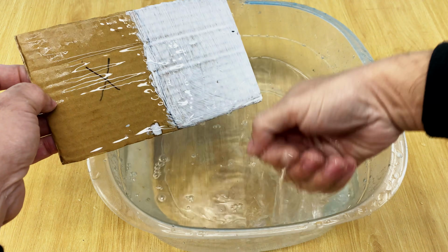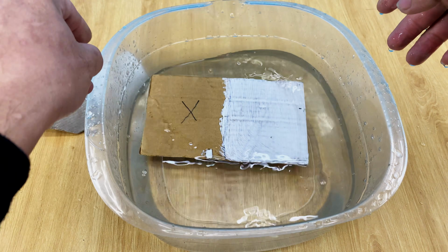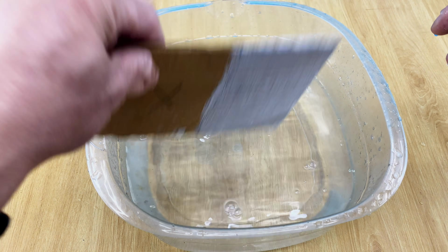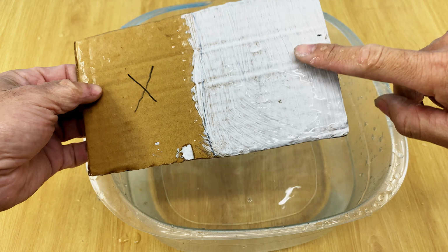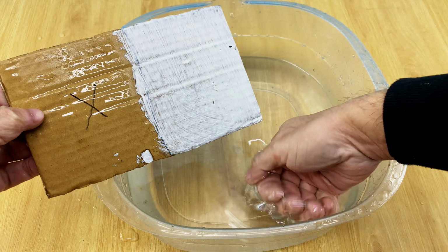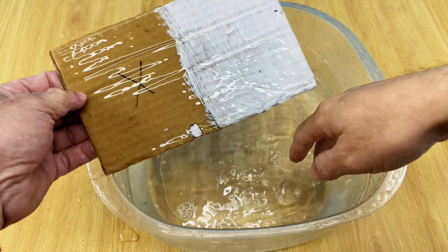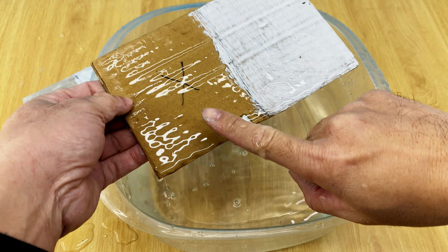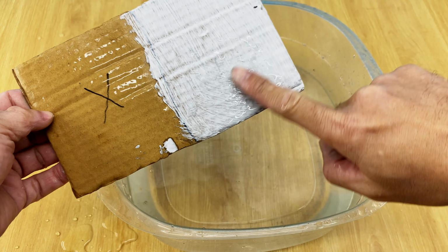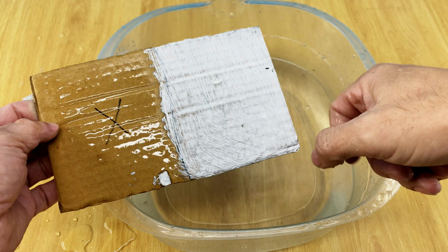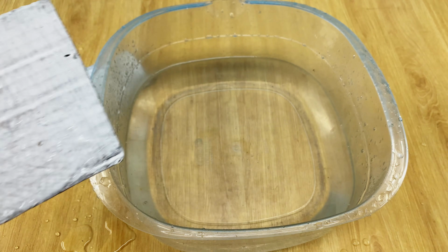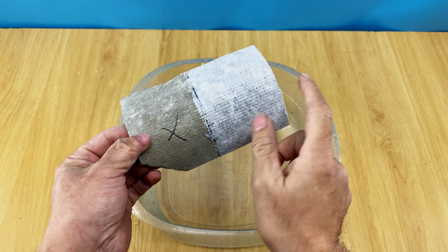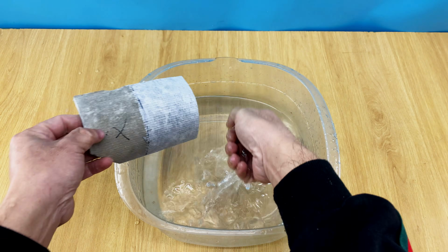Another interesting detail is that the water doesn't stay on the surface for long. As soon as it touches the coated area, the droplets gather together and quickly roll away, leaving the surface nearly dry. Compared to the untreated section of the material, the difference becomes quite obvious. On the untreated side, water tends to linger longer and often spreads out into a thin film instead of forming